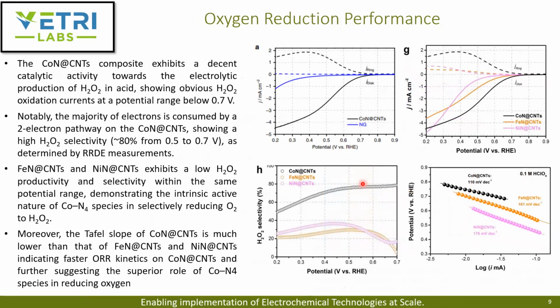And further, they evaluated the electrochemical performance. So they did the ORR measurements in an RRDE setup, where they have a glassy carbon disk, where their catalyst is drop casted, and the platinum ring, which would oxidize the peroxide that is produced during the reduction of oxygen. As we can see here, the cobalt nitrogen co-doped CNTs exhibit good catalytic activity towards electrochemical production of peroxide in acid, showing currents below 0.7 volts, and this is about the theoretical potential for peroxide in acidic conditions.